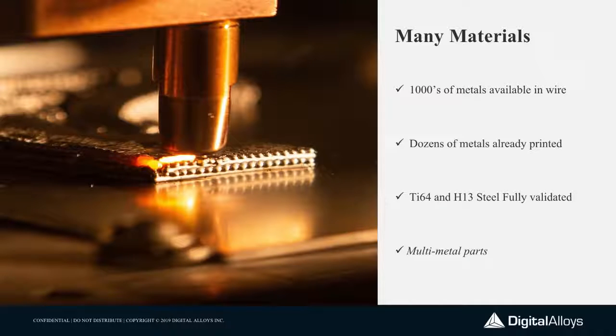So although we are focused on titanium and also tool steel as our first two launch markets and applications, what's exciting is we proved the process is compatible with virtually any metal. Early on in development, we purchased something like 30 different types of metals, anywhere from really low resistivity metals like copper and aluminum to high resistivity metals like titanium. And really dense metals, low density metals, all sorts of different alloys. And we were able to print every single wire we put into the printer, at least as just a little block, a proof of concept that it was compatible. But now in terms of commercialization, we're starting with these two. Inconel 718 will be the next material we release. And then we're looking at a lot of other alloys and grades of metals in this same category, again, of high cost, hard to process.